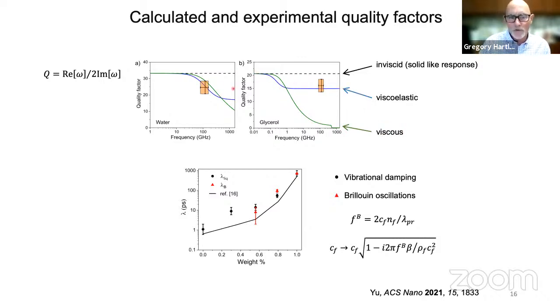So these little boxes are our experimental measurements for these very high frequency vibrations of the thin nanoplates at about 100 gigahertz. So if you have water, you can see in the experiments, both the viscous and the viscoelastic models of the liquid match the experimental results. Another way of saying that is that we can't really see any effect from viscoelasticity for water at these frequencies.